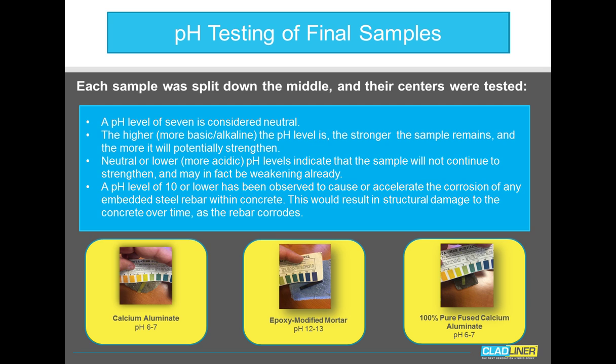And the pure fused calcium aluminate also was between 6 and 7. So what that's telling us is that ultimately, regardless of what happened on the outside, the absorption of the acidity into the core samples resulted in a diminishing of pH in the middle of the product too. So both of those products, namely the pure fused calcium aluminate and the calcium aluminate, absorbed acidity to an extent that even within the matrix, away from the contact areas, they lost strength and pH.